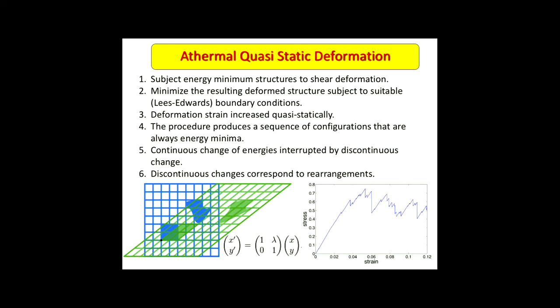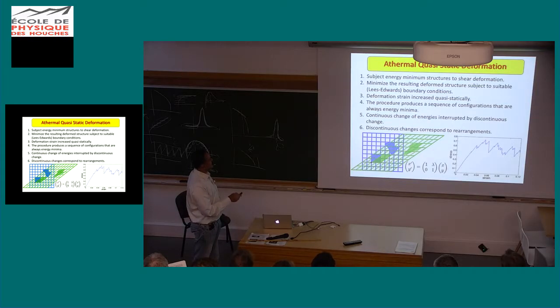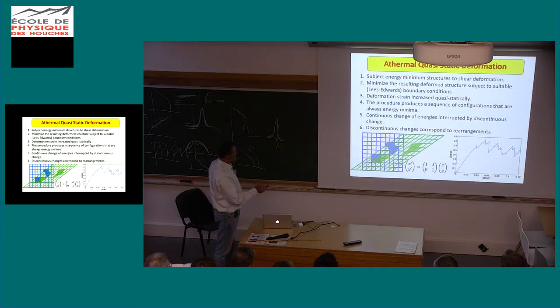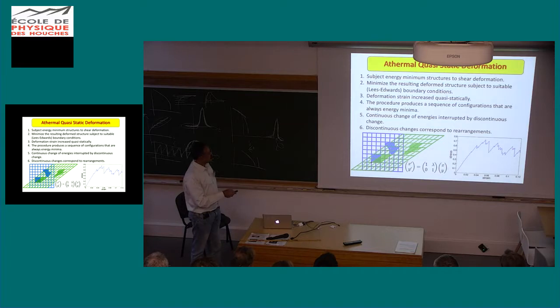Okay. All right, so here is a quick summary of athermal quasi-static deformation. We subject the energy minimum structures to shear deformation by small increments, I forgot to mention, and then we minimize the resulting deformed structures subject to suitable boundary conditions, and the procedure produces a sequence of configurations that are always energy minima. Continuous change in the energies or stresses, as illustrated here, are interrupted by discontinuous changes, and those are going to be the objects of our analysis.